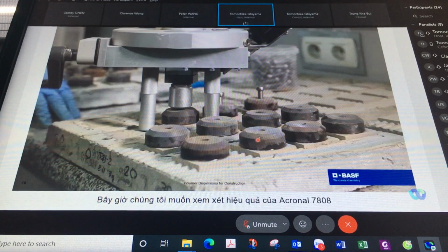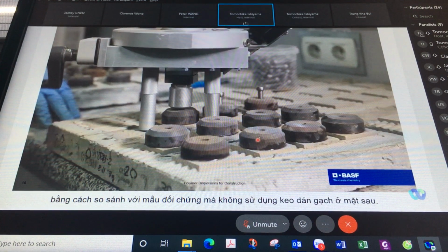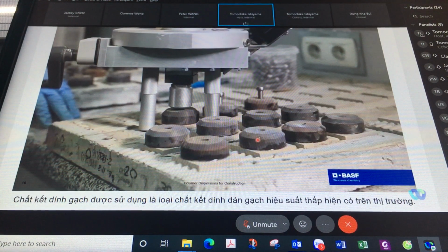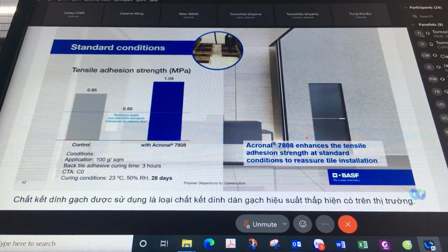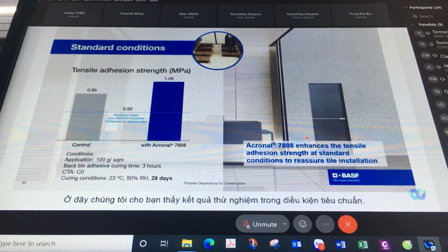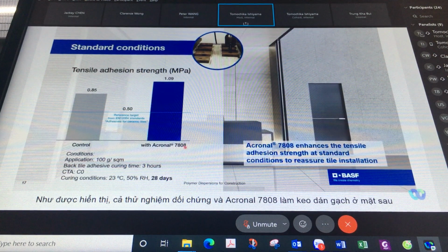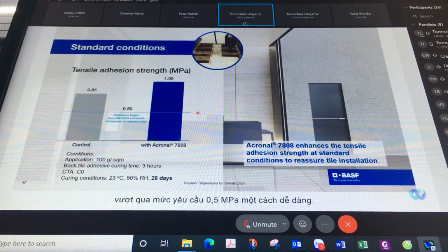Now, we would like to look into the performance of Acronal 7808 by comparing it to a control sample without using back-tile adhesive. The tile adhesive used is a low-performance tile adhesive available in the market. Here, we show you the test results under standard conditions. As shown, both the control test and the one with Acronal 7808 as back-tile adhesive pass the required level of 0.5 megapascal easily.